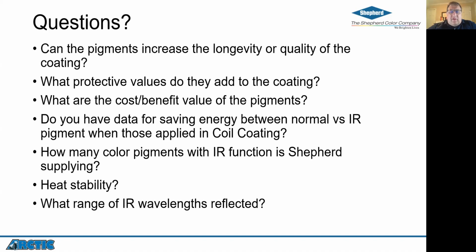What range of IR wavelengths is reflected? Specifically, we're talking about the near infrared, from around 700 nanometers out to where the solar light falls off around 2,500 nanometers. But most of the near infrared energy from the sun is from around 700 out to around 1,200 or so. That is where a lot of that energy is. We're not talking about the far infrared wavelengths that are used for FLIR imaging. Those are around 10,000 nanometers for a room temperature object. So that black body radiation really doesn't play into the use of these pigments.